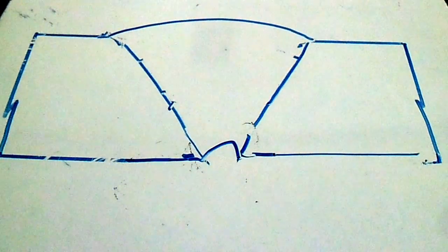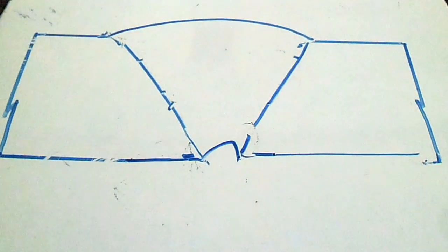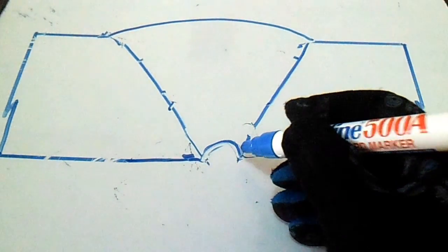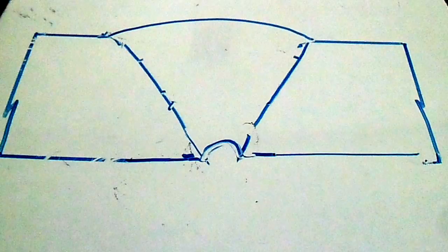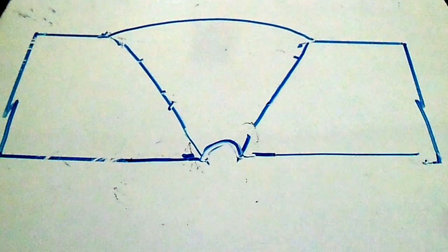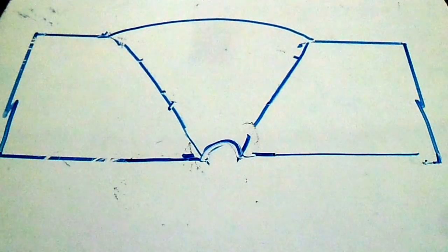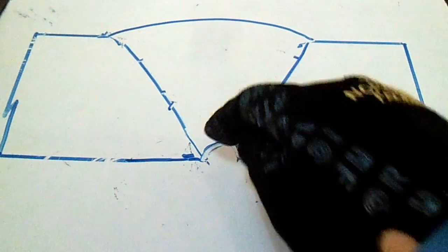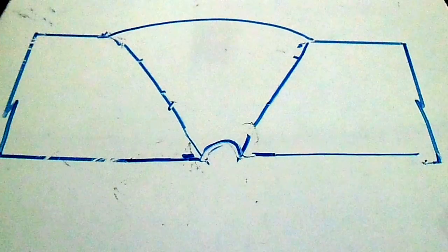this defect is concavity. Okay, so this is a concavity or a suck up. A suck up here is from the root pass. So this is a suck up. The reasons are excessive amperage, high amperage, and incorrect weaving, so that the suck up or concavity occurs. So next defect is,